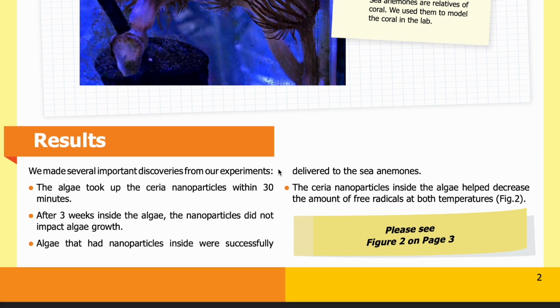Results. We made several important discoveries from our experiments. The algae took up the ceria nanoparticles within 30 minutes. After 3 weeks inside the algae, the nanoparticles did not impact algae growth. Algae that had nanoparticles inside were successfully delivered to the sea anemones. And the ceria nanoparticles inside the algae helped decrease the amount of free radicals at both temperatures.